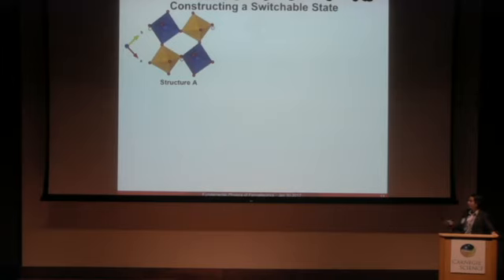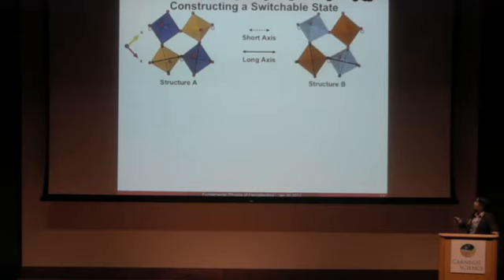So as I said before, the hydrogen likes to remain opposite to the long axis of the nickel that has become nickel 2+. So here in this structure, I'm just showing the one layer that has the hydrogen in it. So in that case, half the nickel are nickel 3+, the other half are nickel 2+, because now this is in the next unit cell. So if we want to create a structure where we move the electron from this nickel to here, we have to switch the ordering of this long and short axis. So looks something like this. Now our other sublattice is nickel 2+. The one that originally had the electron is now nickel 3+. Unfortunately, if your AB plane is not cubic, there's a difference in energy between these two structures. So in relaxed samarium nickelate, this is around 100 meV.